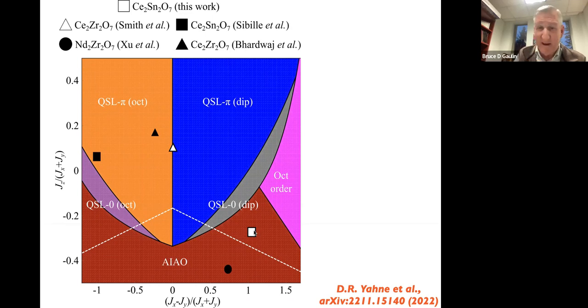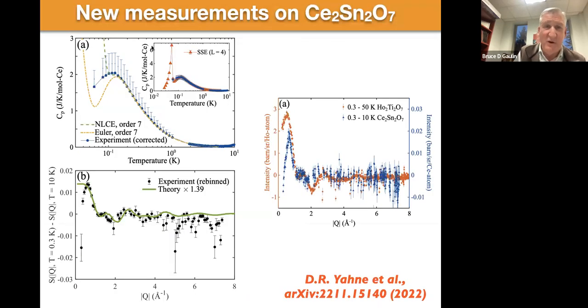It's a conventional Néel state. So actually, if you calculate the heat capacity based on this analysis, you get the calculation that's shown in the inset to this plot in the upper left. This plot shows our heat capacity data, and the fit to it in red. The parameters in the Hamiltonian that are extracted give you a phase transition at very low temperatures, like 40 millikelvin, which we don't access in our experiment. So the conclusion from the microscopic Hamiltonian is that if you go to low enough temperatures, this system should order into what's otherwise a conventional Néel state, and it's the dipole moments that should be ordering.